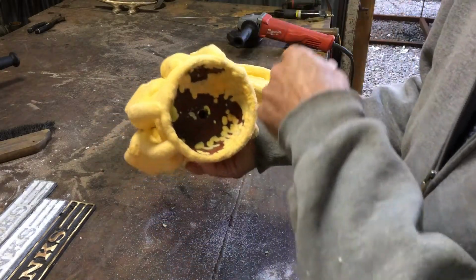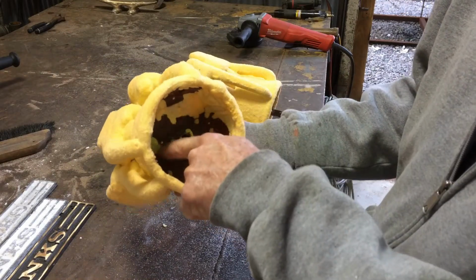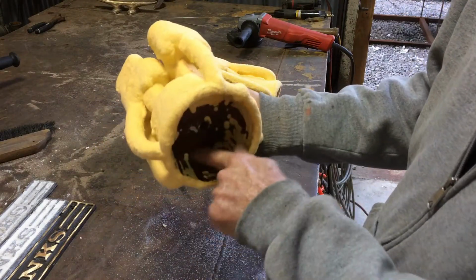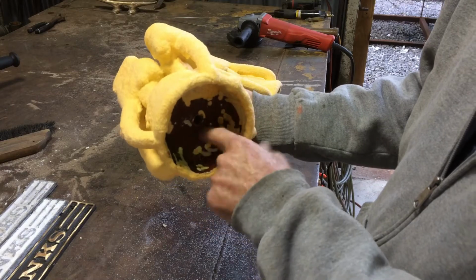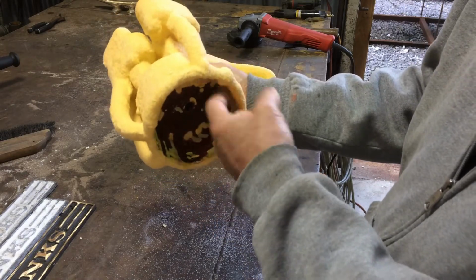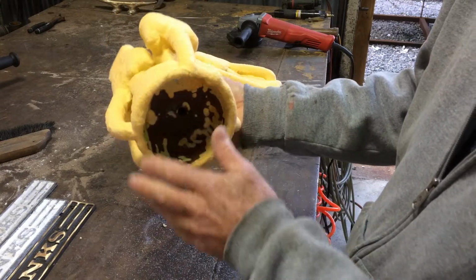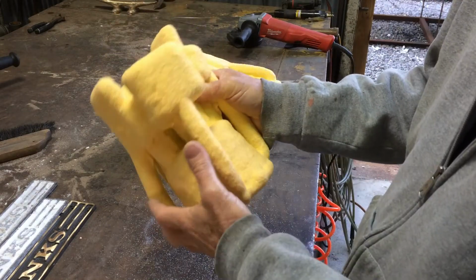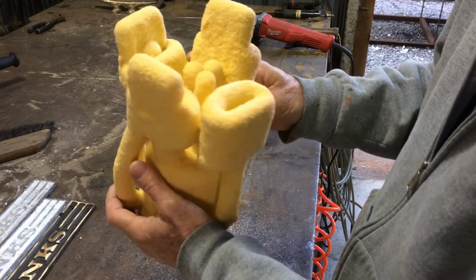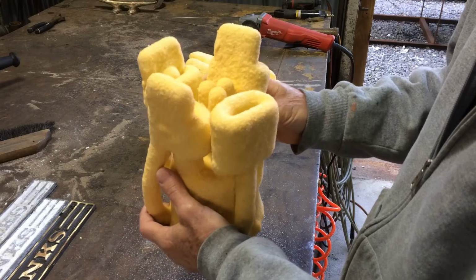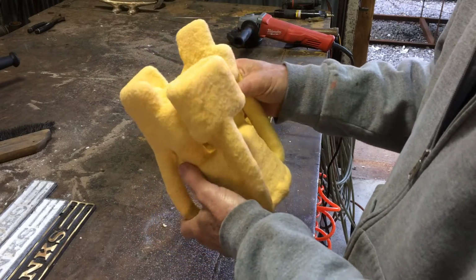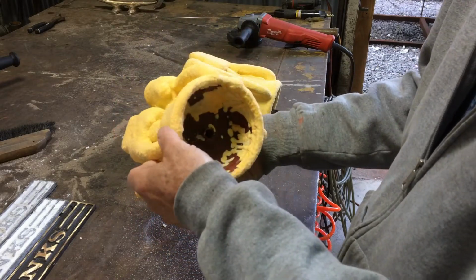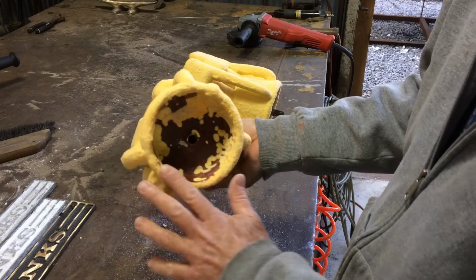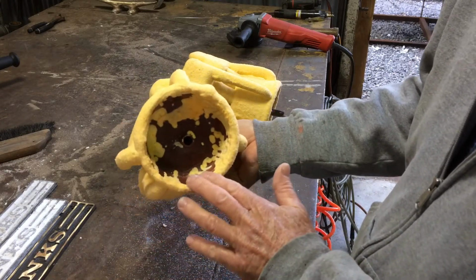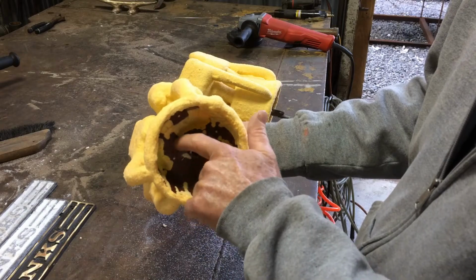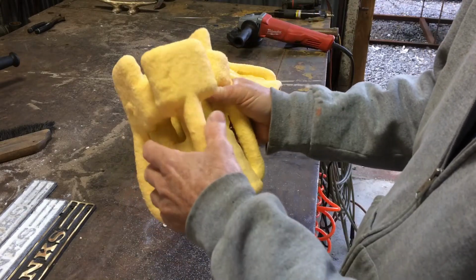So before I put it in the kiln, I take the torch and just warm up the cup and remove all of this wax, and at the same time I remove the plastic cup and clean up this edge. And I have had a very good success ratio of burnouts without damage to molds. So that's what we're going to do now. I'm going to grind this edge to clean it up, and then I'm going to use the torch to get this wax out, and then we'll put it in the kiln and do the burnout.